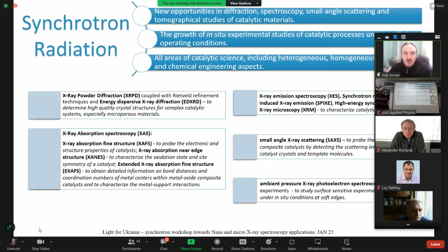For example, if we have a phase with nanoparticles in the size of 2 nanometers or about this, X-ray diffraction is just not useful. We cannot see these particles. There are also methods that use X-ray spectroscopy. I will say a few words about this later. There are also different methods such as X-ray emission spectroscopy, and small angle X-ray scattering, which is very useful, for example, for analysis of the porous structure of materials.